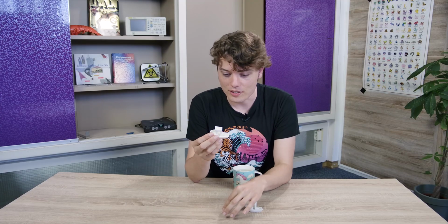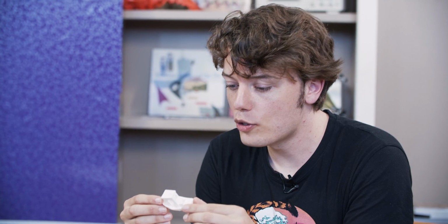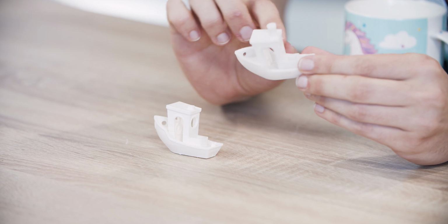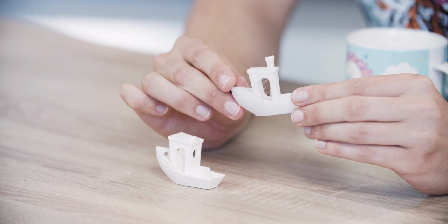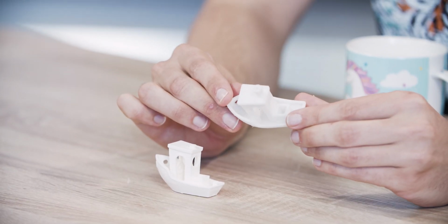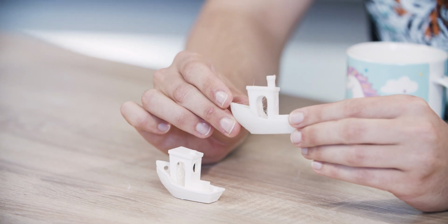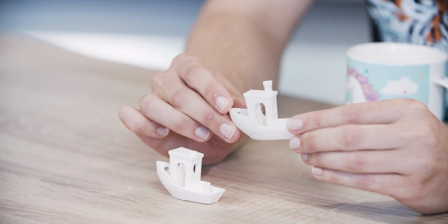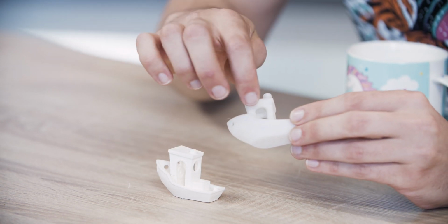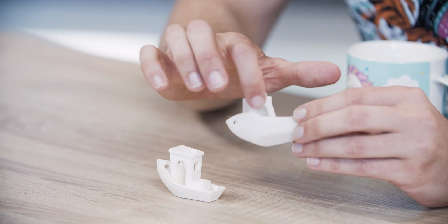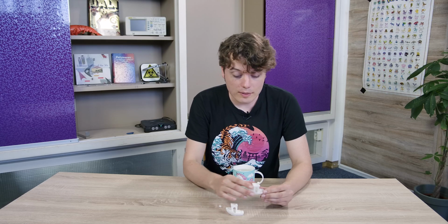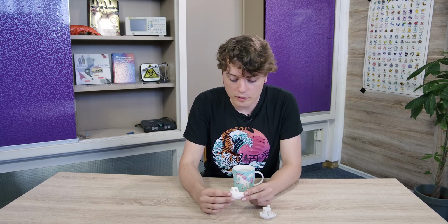I accidentally broke this off. Didn't come like this out of the printer. So, well, if you zoom in a bit, you can see that my plastic still has some whiskers after the printing. I think this has something to do with that the temperature was a bit too hot for printing. You also see some small defects where there wasn't enough plastic and you got these small openings. Yeah, it's okay. I mean, it printed the thing and it looks like the one with the material which I purchased from the store. So I can say this is quite a success and I'm quite happy with it.